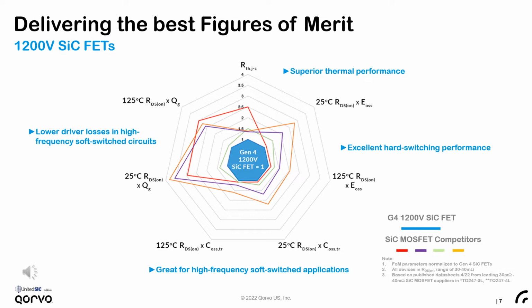But as one can also see here, they offer an excellent RDS(on) times COSS, both at room temperature and elevated temperature up to 125 C, which we represent here as a hard switching figure of merit. These devices are also great for soft switching. Their COSS time related is lower for a given RDS(on) than their peers. So this is excellent for high frequency soft switching.